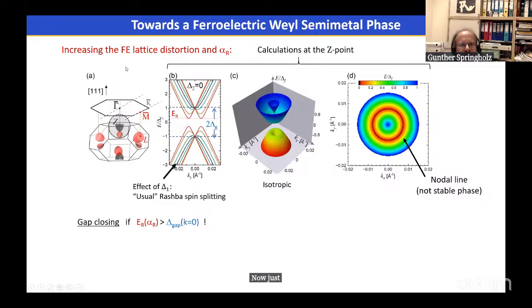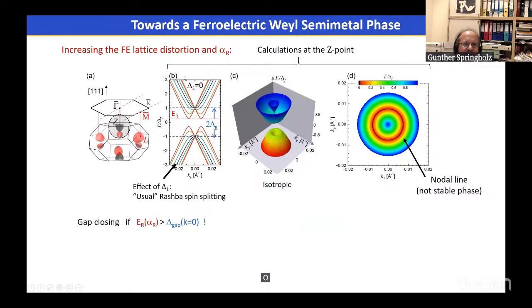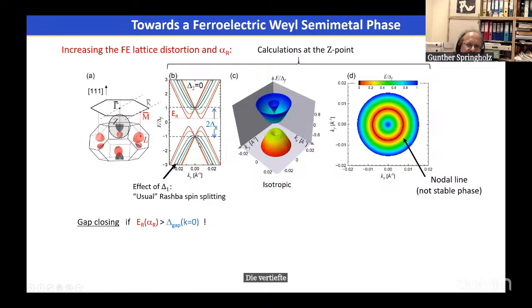Now, just shortly, what happens if we increase the ferroelectric polarization or lattice distortion? Then this Rashba splitting gets larger and larger, as shown here. So these are curves calculated at the Z-point for different ferroelectric polarizations and different magnitudes of the Rashba parameter. So one can see that if alpha gets larger and larger, we have a stronger and stronger downward shift of the minima of the band gap.